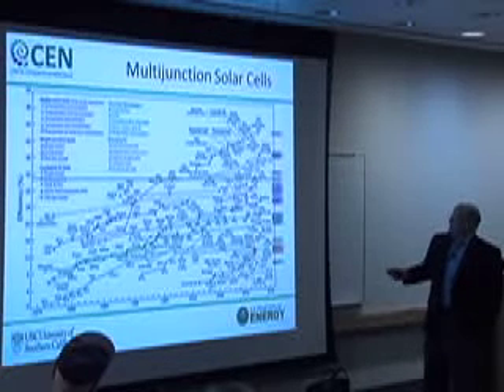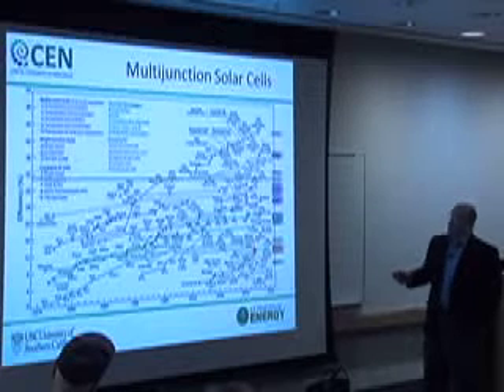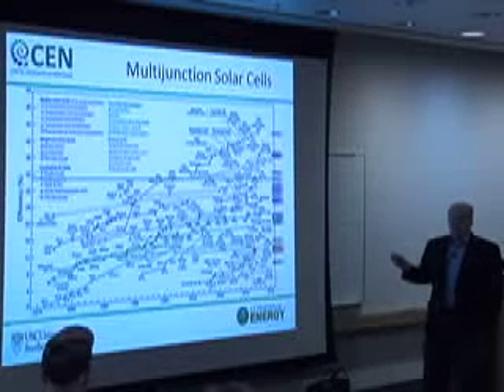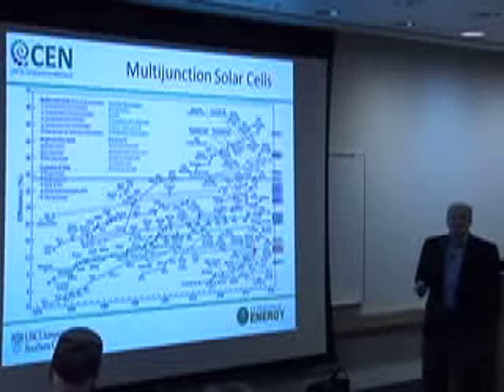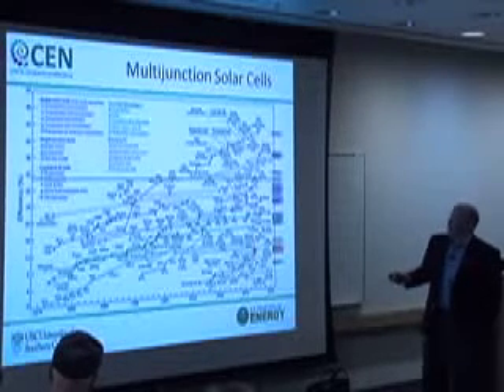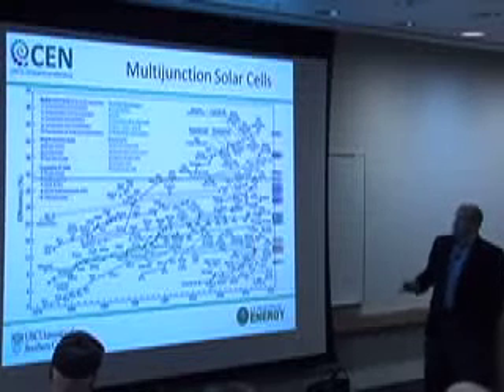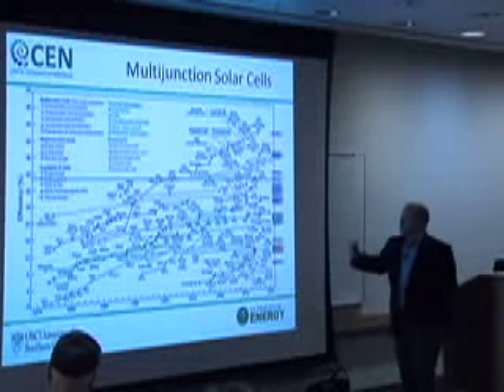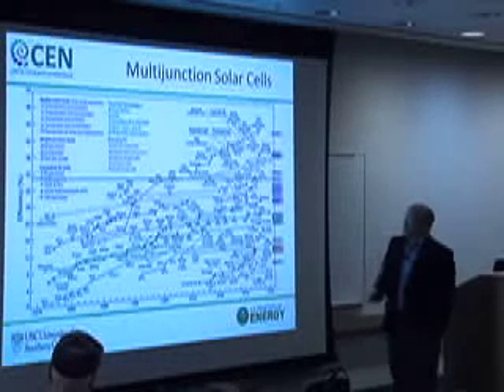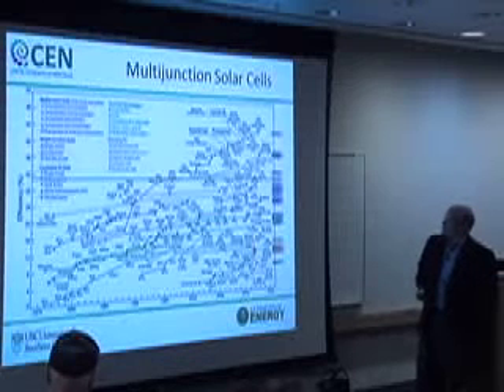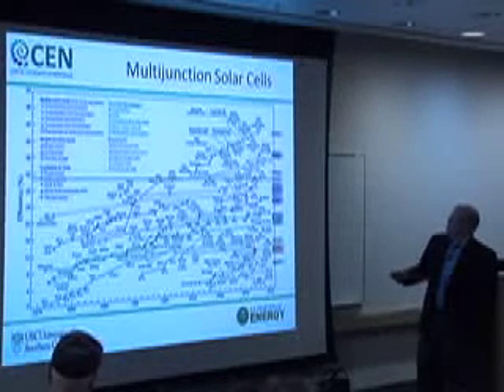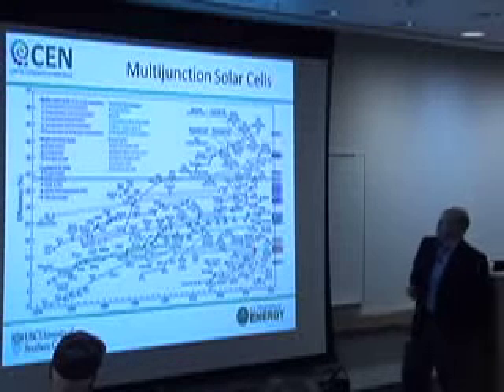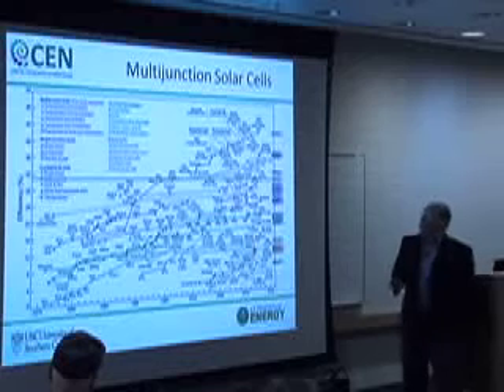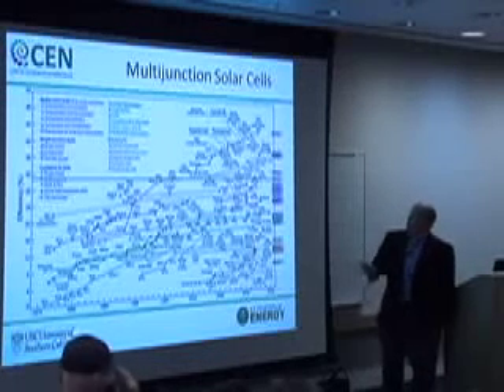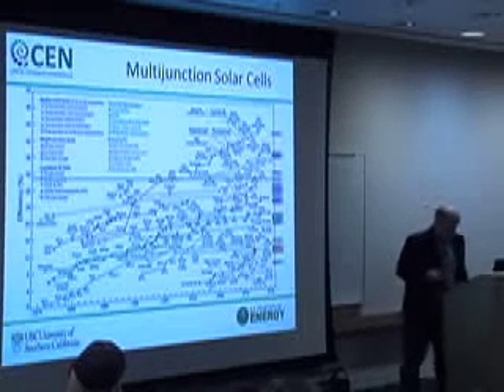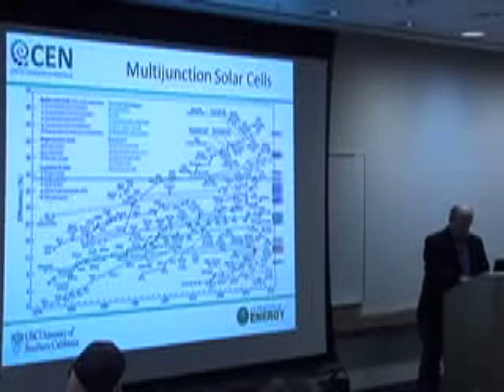And as far as I know, there's only one device, a recent work out of Alta Devices, a gallium arsenide solar cell, that's actually achieved very close to the Shockley-Queisser limit in efficiency. Most of these other dots here, which represent the best research devices for a particular technology at the time, at the year that they're plotted here, fall well below that. The only ones that exceed the Shockley-Queisser limit are the multi-junction solar cells. So that's why we targeted this, and I don't know if I'll convince you that we're on the right track, but that's what we're trying to do.